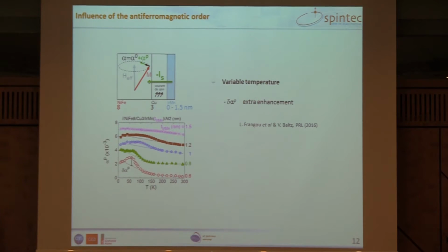So to go a bit further, we've varied the temperature. So here are some experimental results where we show the absorption as a function of temperature for different iridium manganese thicknesses. To ease the reading, the data are shifted vertically. And what is interesting here is that we can see a little bump, which we call delta alpha P, and which occurs at a given temperature. And this temperature actually depends on the thickness of our film.